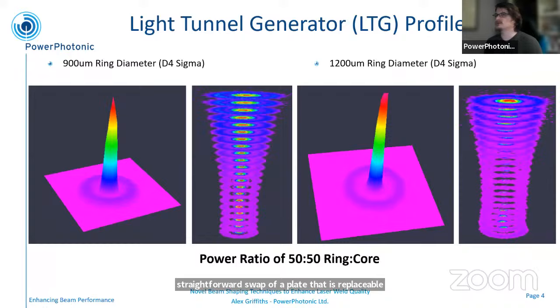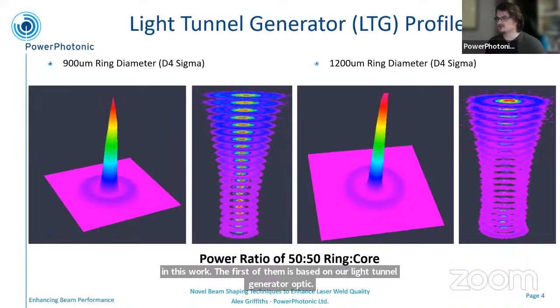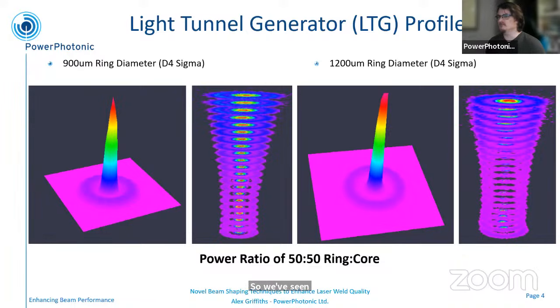So there's two different beam shapes that we're looking at here in this work. The first of them is based on our light tunnel generator optic. We've seen already, it's quite widely known that the welding can be improved with a core and ring setup of your intensity profile, where you have the central core doing the weld and this ring of intensity that applies some heating around to the surrounding area.